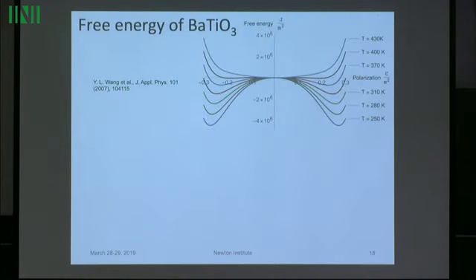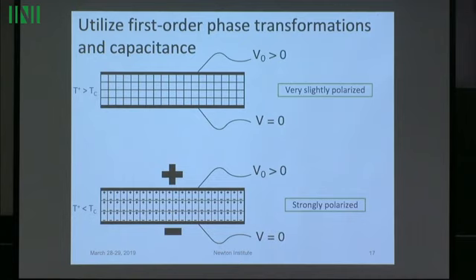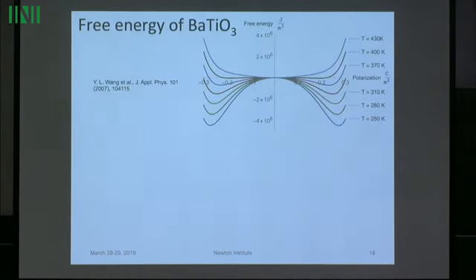Okay, so already I'll jump to the simplified model. In barium titanate, we do have a quite nice, measured with great care, simplified model for the free energy. Strain is gone, so it's measured in an experiment like this kind of experiment. Maybe there are domains, maybe there are strains, but anyway, just the polarization is measured, and a free energy function is fit to that data. So we're going to use this free energy function. It's actually a triple well potential. At high temperature, there's a single well, and at low temperature, there are two wells corresponding to plus or minus m.